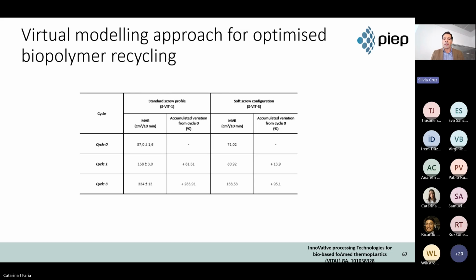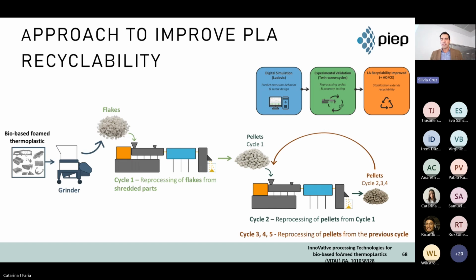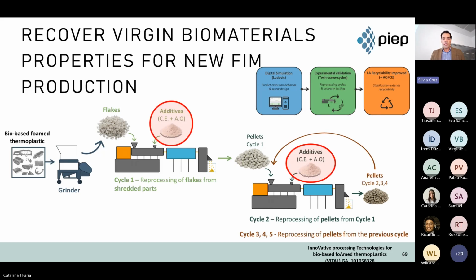It's more relevant than the optimization of the parameters on the compounder, and it was quite interesting, this result. So the final step was, okay, we know that the material suffers some degradation on the recycle. We know that with increasing of the cycles, the material is getting more and more degraded, but we want to study and try to identify what was possible to do to avoid this level of degradation. So we decided to test some additives.